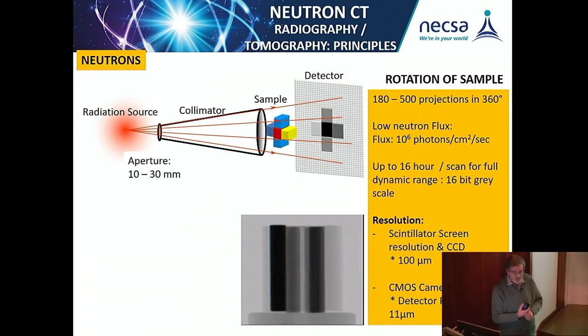A scintillator screen is a screen that changes the neutron energy into normal light photons that can be detected by a CCD, a charge-coupled device. And the resolution there is limited to 100 micrometers, although with newer CMOS detector systems, the resolution can go down to 11 microns or even 5 microns, with systems available at the Paul Scherrer Institute in Switzerland, as well as at the FRM2 München facility at the Technical University of München.